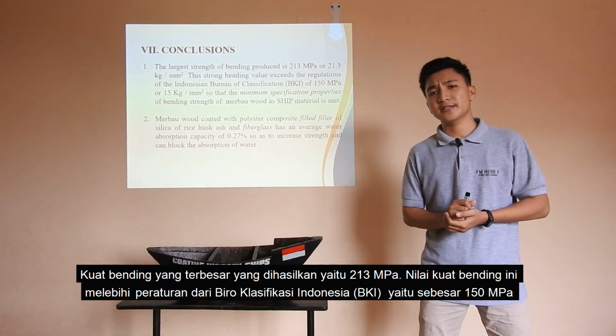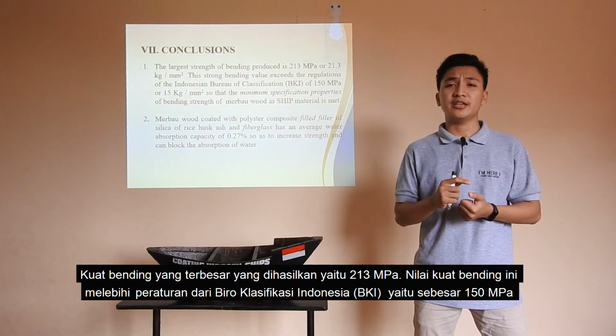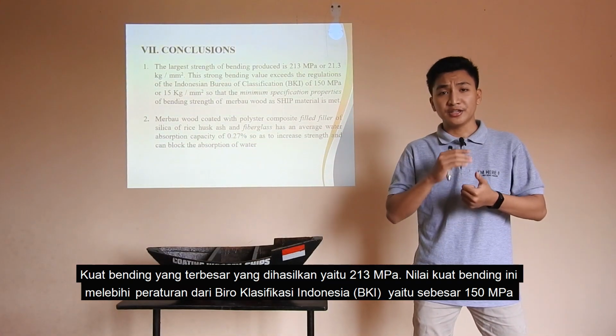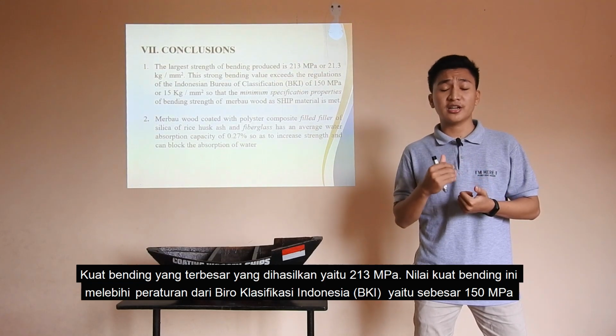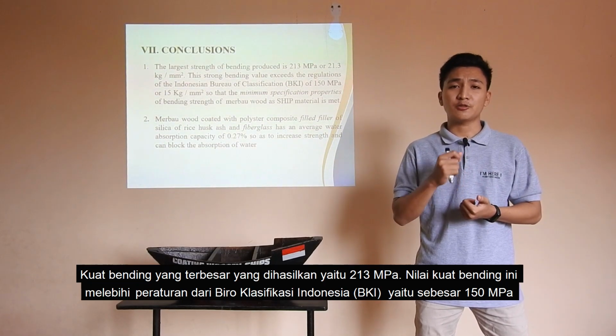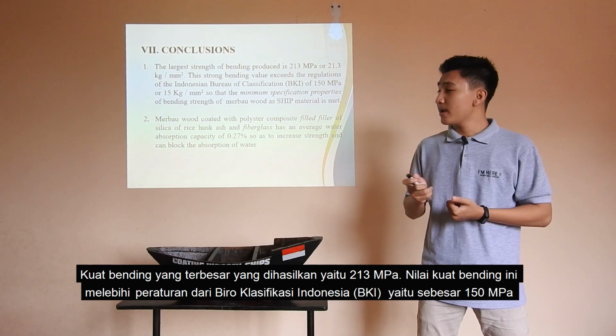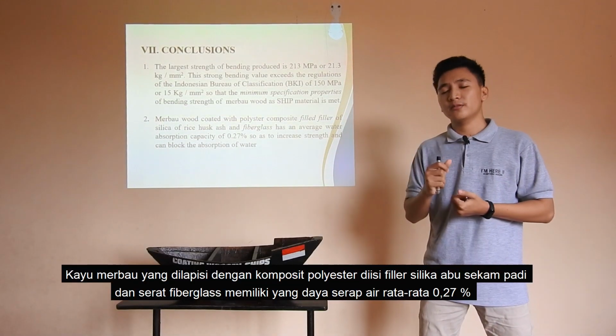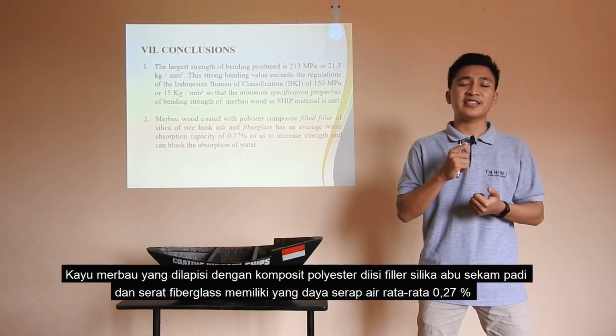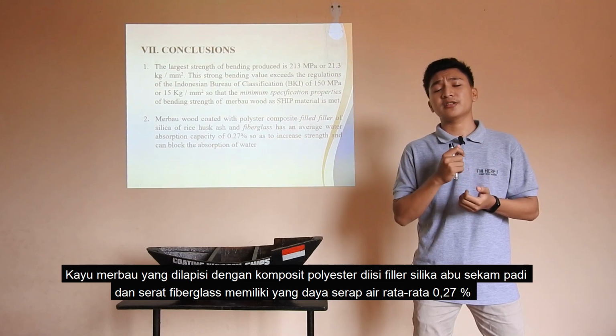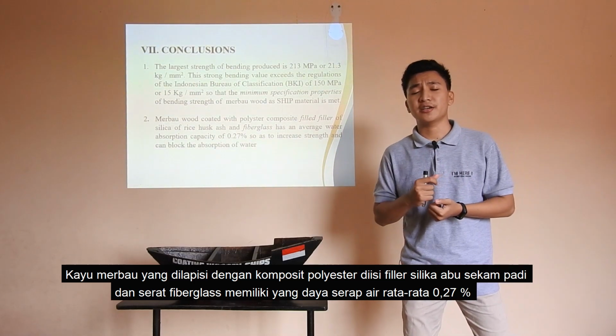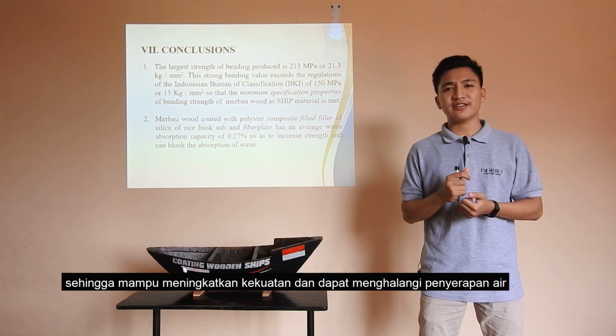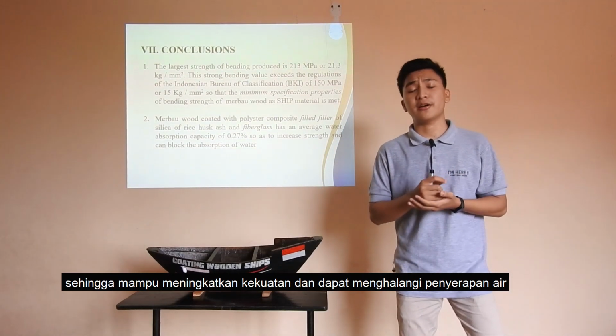So the conclusion is the biggest bending strength is 213 megapascal. This value exceeds the Biro Klasifikasi Indonesia standard, that is 150 megapascal. Merbau wood coated with polyester composite with silica filler has water absorption capacity 0.27%, so that it can increase strength and protect from water absorption.